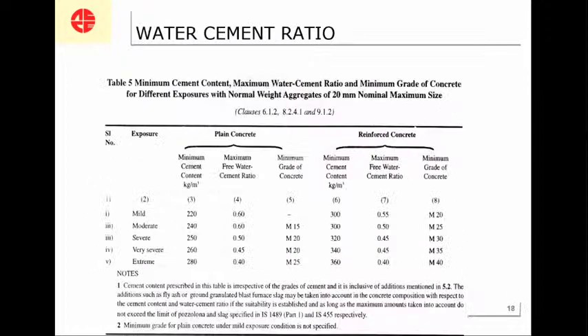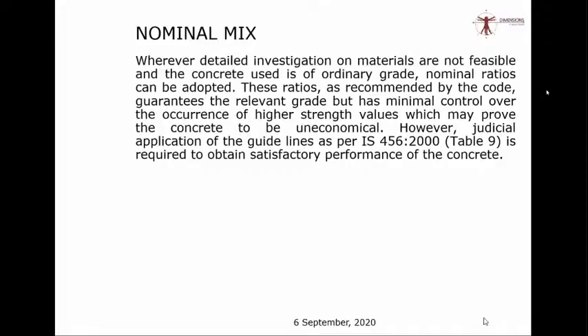This is table number 5 of IS 456, which tells you one very important parameter. See, if you are using plain concrete, the minimum cement content you should use in kilograms per m cube of concrete for mild exposure conditions is 220 kilograms. For moderate, it is 240. But today we are going to talk more on structural concrete. It is not plain concrete. So there is enough and more probability that you will land up in a much higher strength.